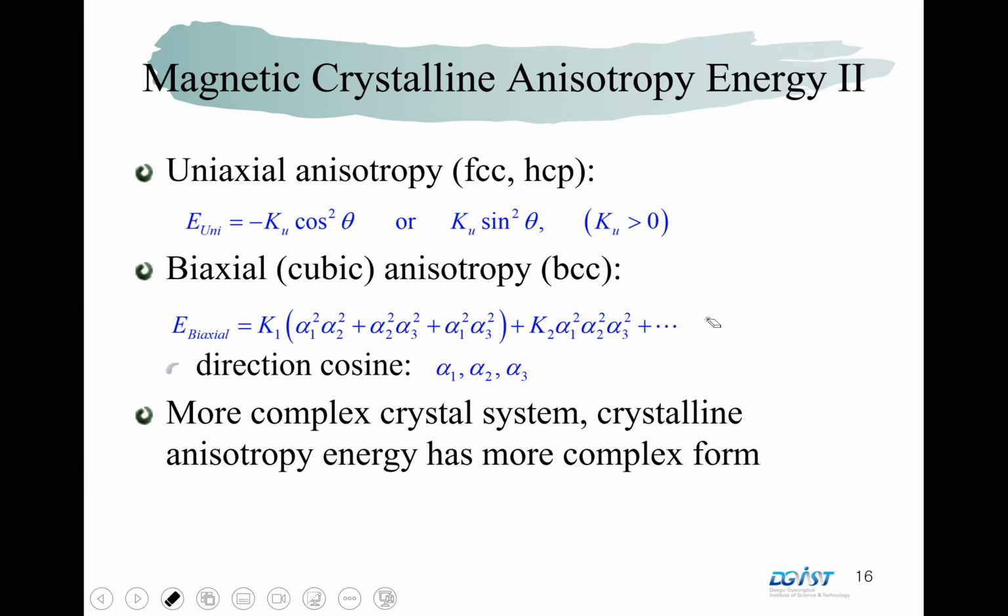Here, L10 ordering means some kind of crystal structure. In that case, they prefer a certain crystalline direction, and when we grow the cobalt platinum or iron platinum system, we adjust the preferred direction heading to the film normal.